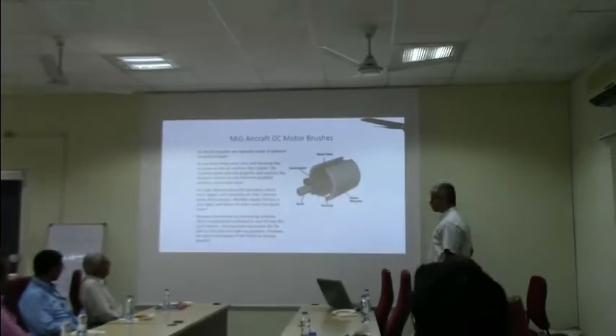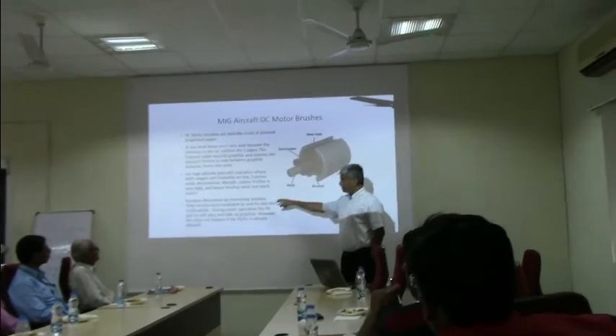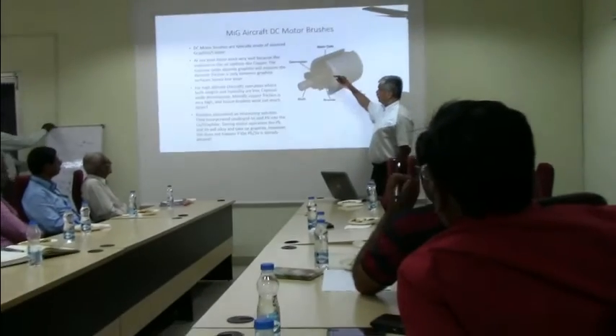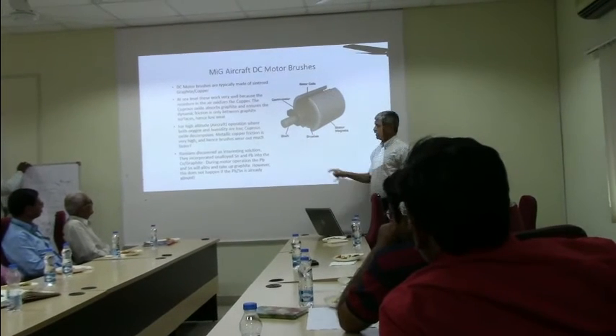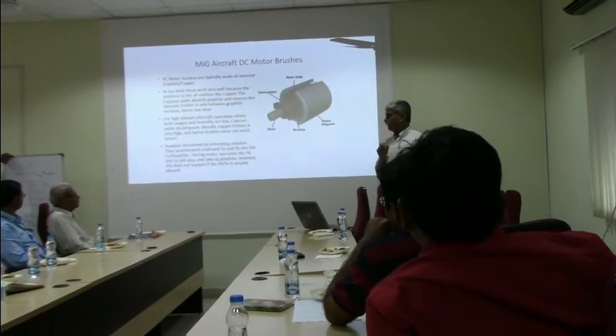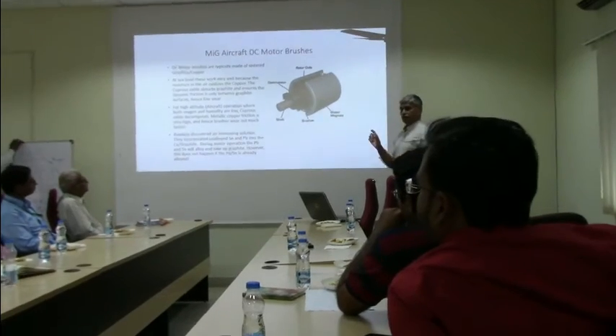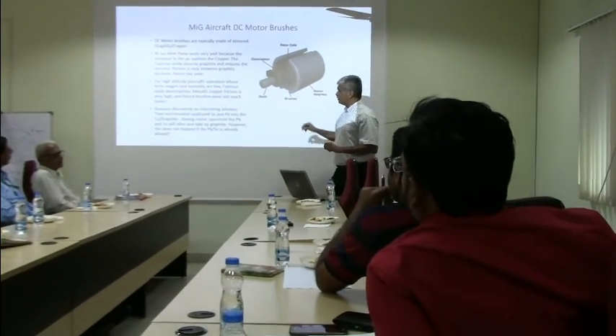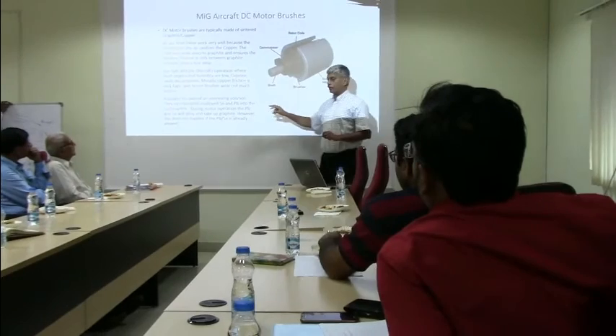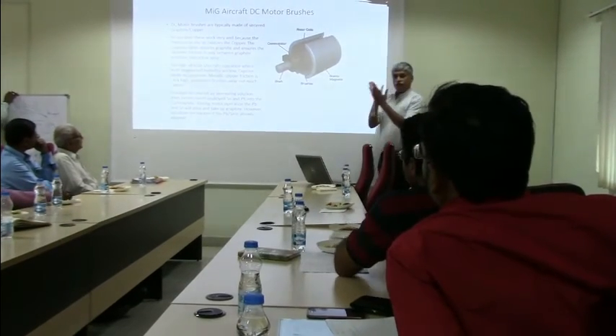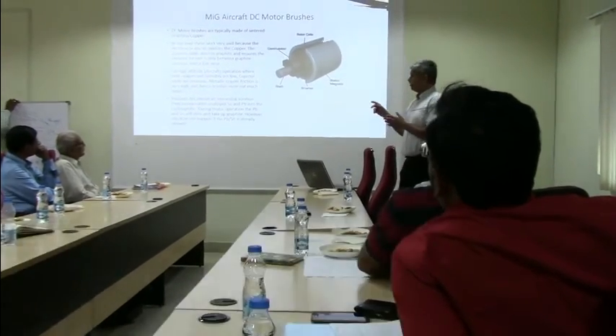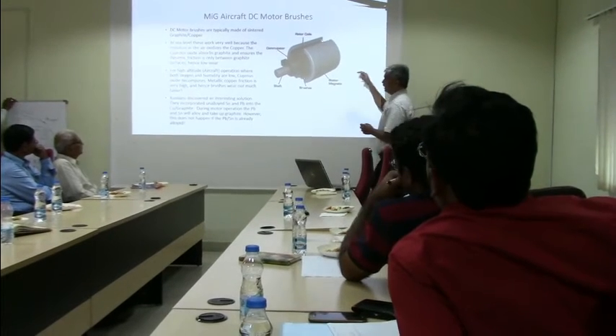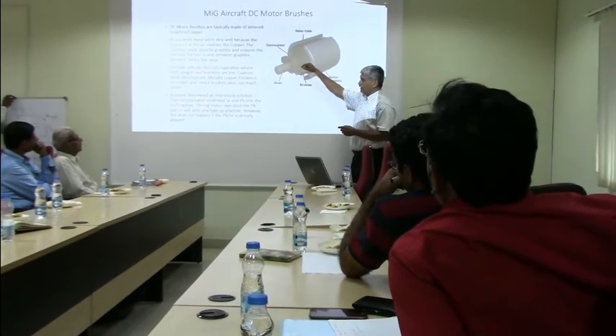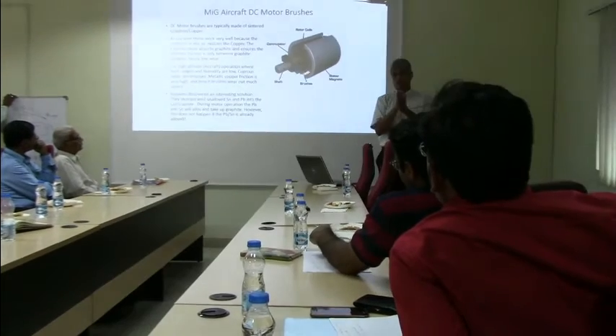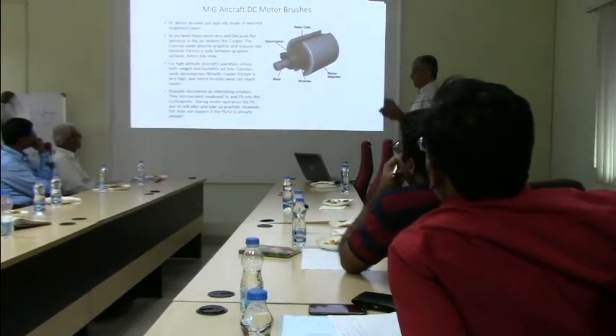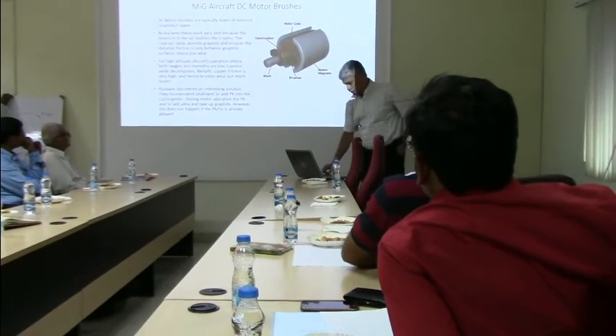Now the Russians had discovered a very interesting solution. What they did was they incorporated lead and tin into the copper graphite. And there is also another interesting trick, which is that the lead and tin should be separate, it should not be alloyed. Because if it is alloyed, then it will not absorb graphite. But during the friction operation, it forms an alloy where the graphite gets absorbed instantly into that lead tin alloy, and that's where it starts the friction. So that way you can make it last for long.